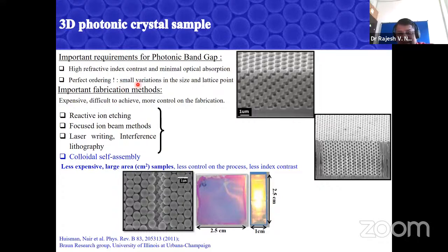So keep this in mind: people try many ways to make the sample. One way is semiconductor fabrication, where you have electron lithography and reactive ion etching. Then you try to make these kinds of structures. Basically, you take a silicon wafer and make angle etching. You can see that there is a variation of refractive index. The region between these circles is air and the other medium is silicon, so you naturally get a variation of refractive index between the air and the silicon.